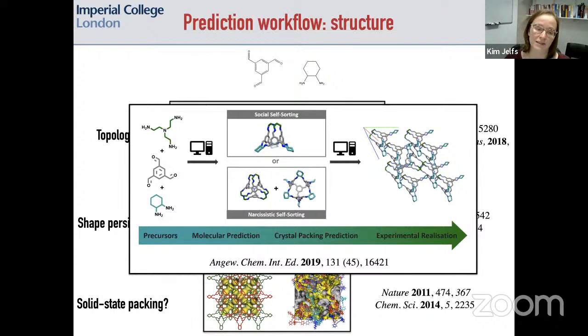And this paper from a few years back is an example of where we first put all of these elements together. On the left-hand side, we had a more complicated case where we had 3 different precursors. So we would predict how those 3 different precursors would combine at a molecular level. Because there are 3 precursors, it's more complicated, because you could get social self-sorting, where all 3 precursor molecules arrange into one supermolecule, or you can get 2 different 2-component systems instead, known as narcissistic self-sorting. And obviously those different outcomes give you totally different systems, totally different porosity and so on. So we predicted the most promising systems that had the hat type shape that I show at the top. And then our experimental colleagues went and synthesized the ones we predicted and got the hits in the lab.